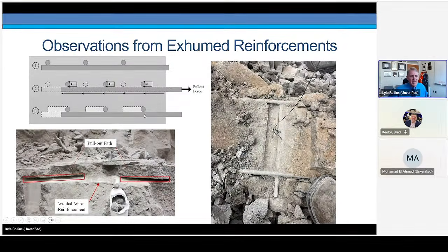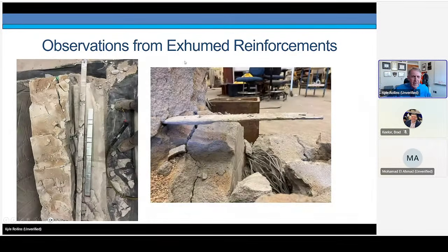We exhumed the reinforcements, and you can see that here as we pull on this longitudinal bar, the crossbars develop passive resistance on their face, even though we're treating it as a frictional thing, and a gap forms. So as we're pulling this way, you can see the gap that forms in the LCC behind that crossbar. After exhuming it, you can clearly see that bar is pulling to the right, and we basically pulverized this material behind it. For the reinforcements, they start out looking like this. As we pull out the rib strip reinforcements, in a number of our cases, it looks like there's still some LCC adhering to the reinforcement as it's being pulled out.